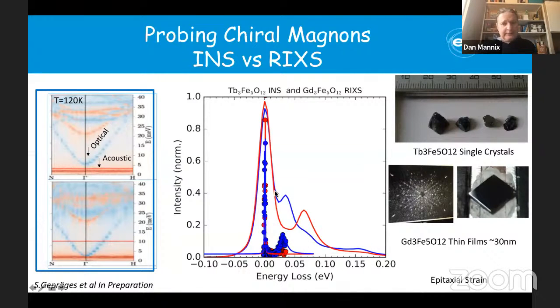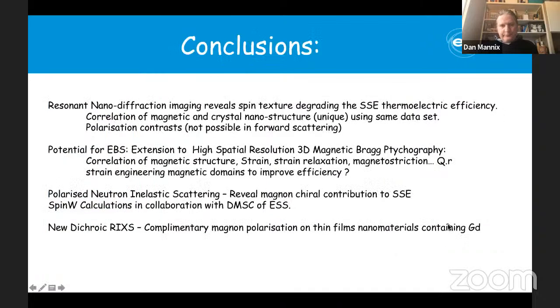And so we've been able to make a comparison really between what we've measured in single crystals with thin films. So the conclusions really of the talk: first of all, there was this nano diffraction, which reveals a spin texture that seems to inhibit the thermoelectric efficiency. And we can develop a methodology to correlate magnetism and crystal structure with these data sets, also using this polarization contrast, which wouldn't be possible in forward scattering.